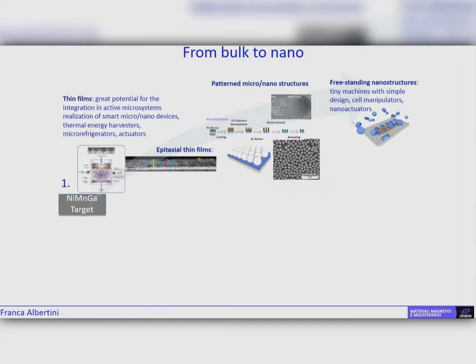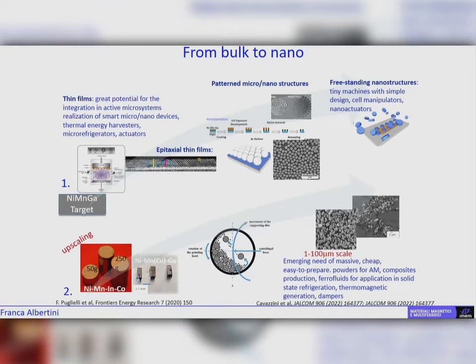and they could be used as machines and for many applications, including bio applications. We have also followed another path in our research due to the need of material in large quantity and with very repeatable properties for the magnetocaloric application. We have set up a technique for producing up to 250 grams of magnetocaloric materials. In this case, it was the giant inverse nickel manganese indium cobalt.